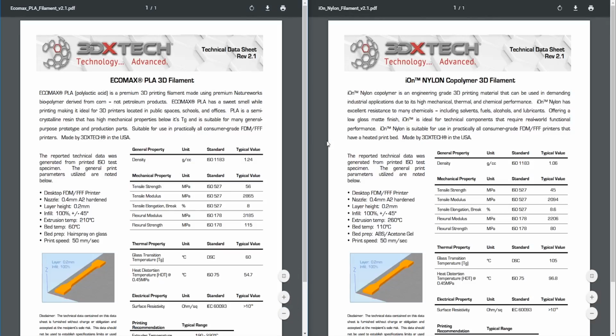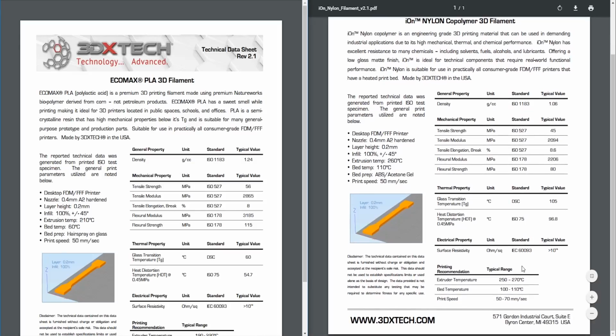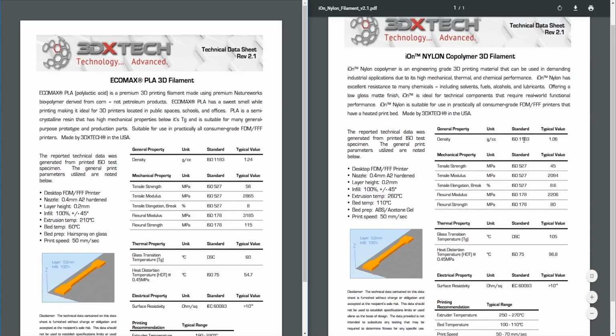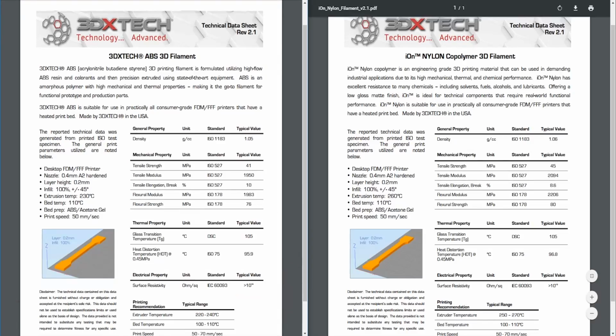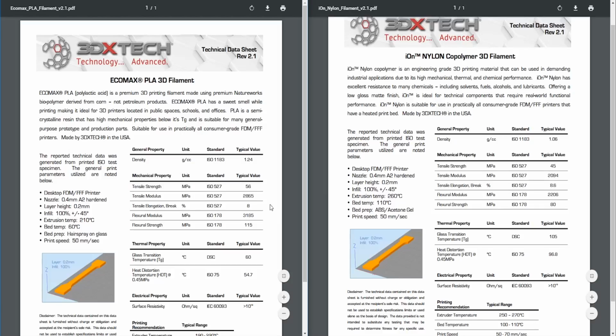So we have our PLA on the left and ion nylon copolymer. It says it's for a low gloss matte finish, but it doesn't really tell you what the other polymer is. Anyways, very low density, already seeing this, even lower than ABS. Oh, it's about the same as ABS. Stiffness, 56. Tensile strength, it's 11 lower. Quite a bit lower stiffness, just a little bit more elongation, quite a bit lower flex. Actually, the strength is almost on par, pretty much on par with PLA.